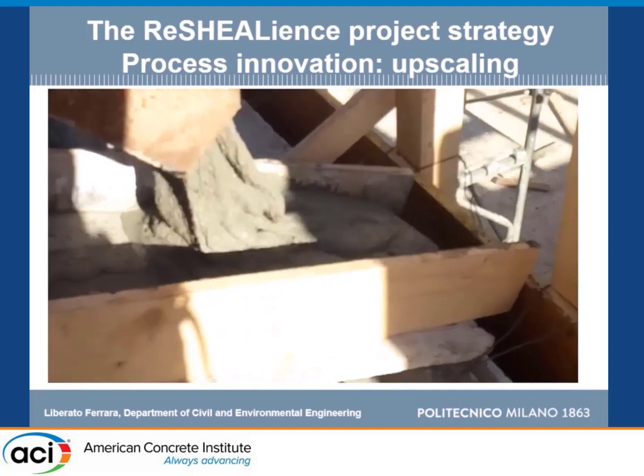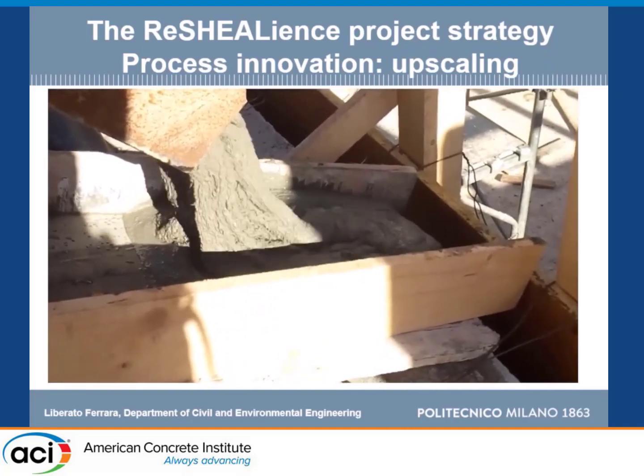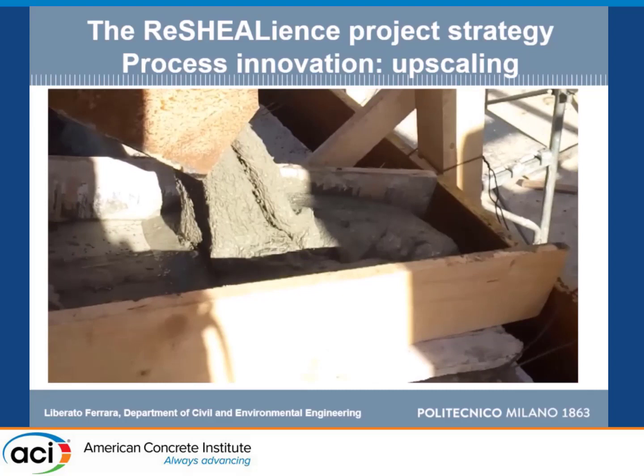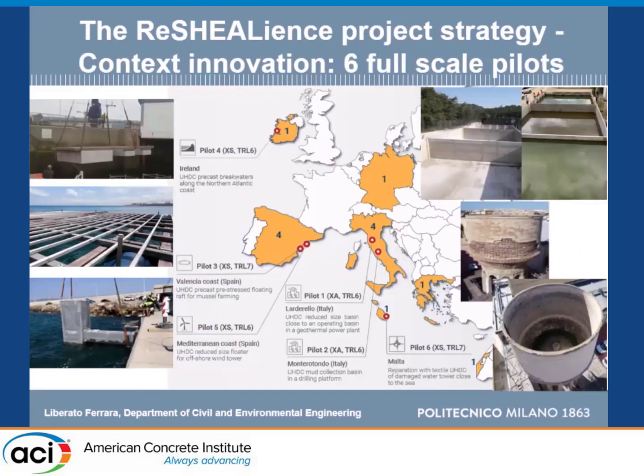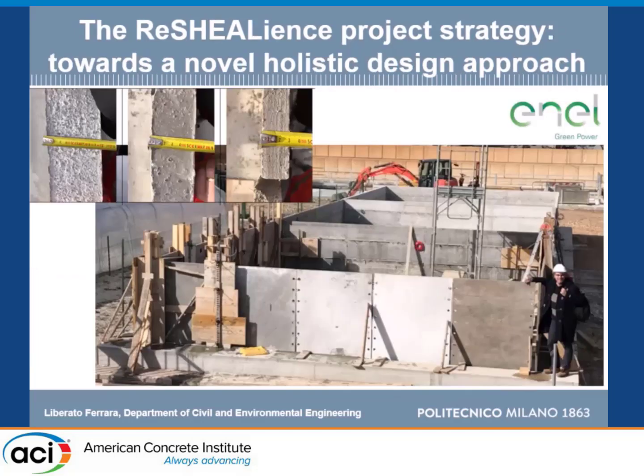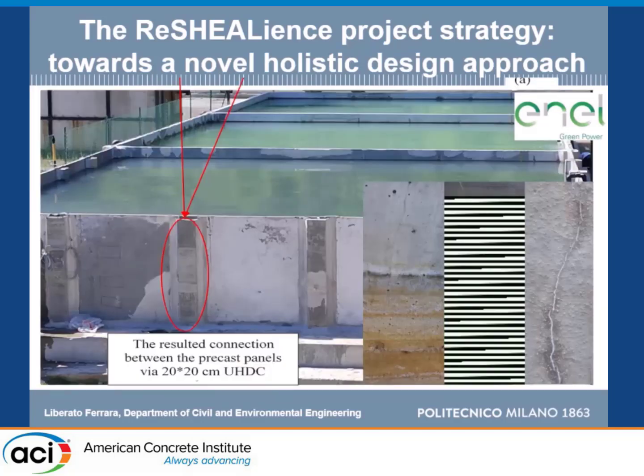Then we had to scale up from the lab to the construction site, not mixing 50 liters, but mixing 500 liters per batch. So there was also education of construction companies to this. And we used these materials in 6 full-scale pilots, 2 in Italy, 2 in Spain, 1 in Ireland, and we retrofitted this water tower in the island of Malta. This is one of the Italian pilots, ordinary reinforced concrete, 10 centimeter thick, precast UHPC, 3 centimeter thick. And you can see here the load validation.